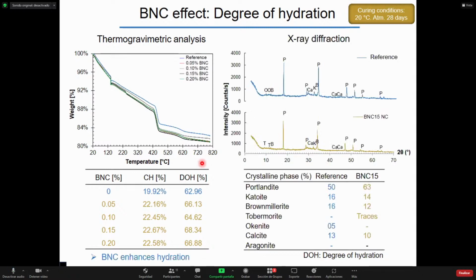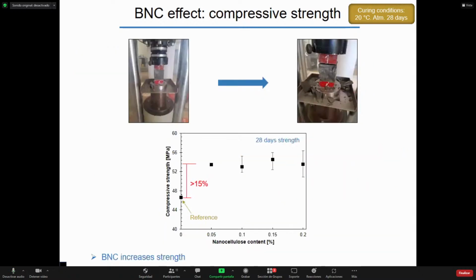We also saw this in the X-ray diffraction test, where the content of Portlandite increased while the anhydrous cement decreased. And we also saw some small quantities of calcite. These results indicate that bacterial nanocellulose enhanced hydration over time. This is probably the reason why the cement with bacterial nanocellulose was stronger after 28 days of curing.